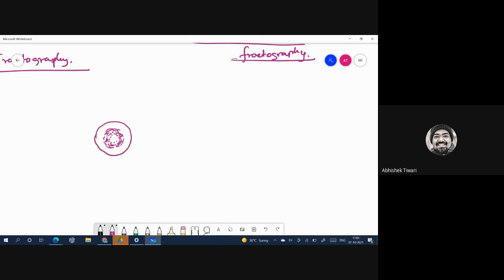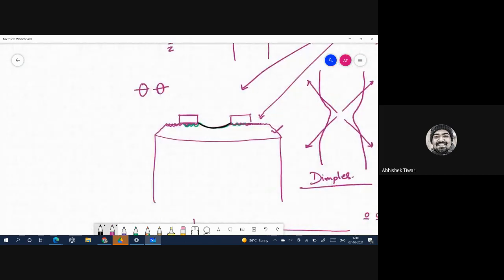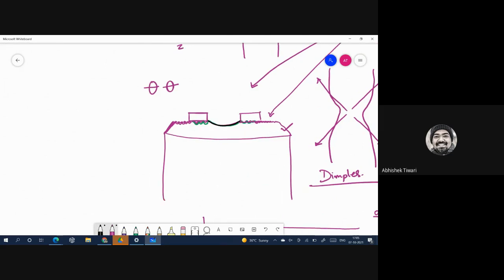And then you will have a radial region surrounding that where the material has failed at 45 degrees, or in the direction of maximum shear stress. So this part I'm talking about is called the radial region. This has gone at approximately 45 degrees because of the shear stress. So what has happened is the material was not able to take load, and then this micro crack propagated until these points, and after that it broke in shear. Okay, so this part is called the shear lip.